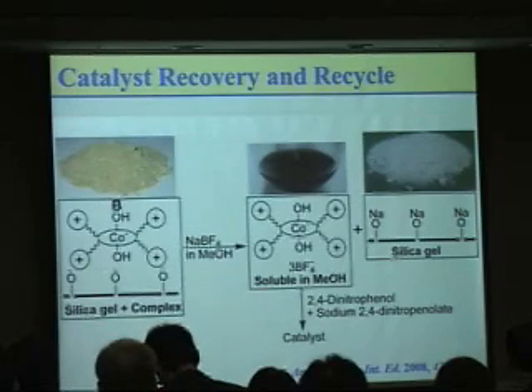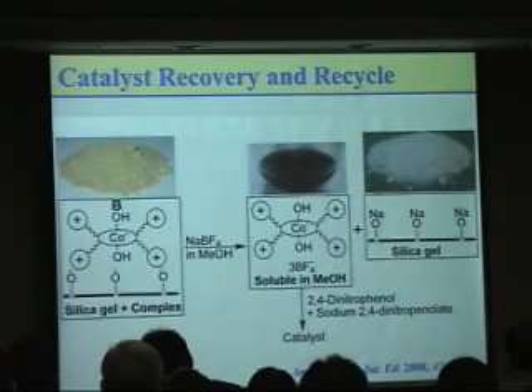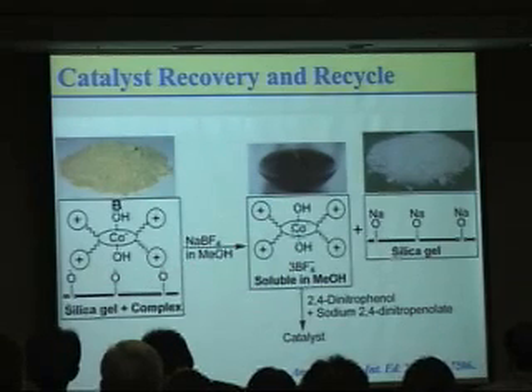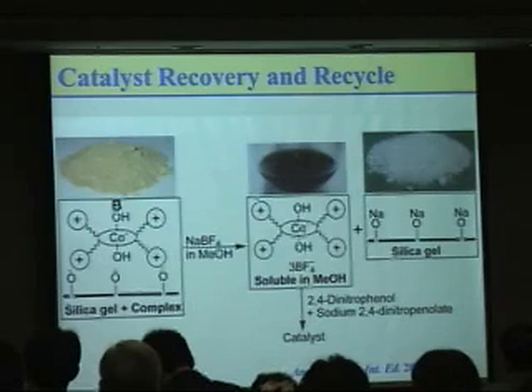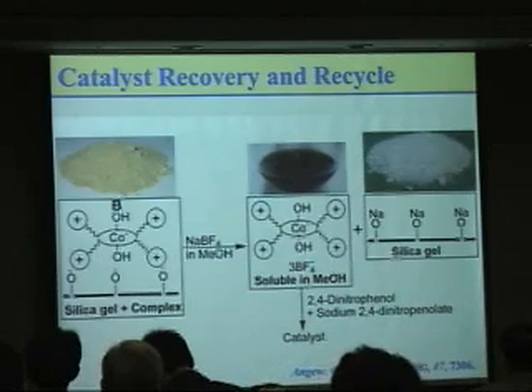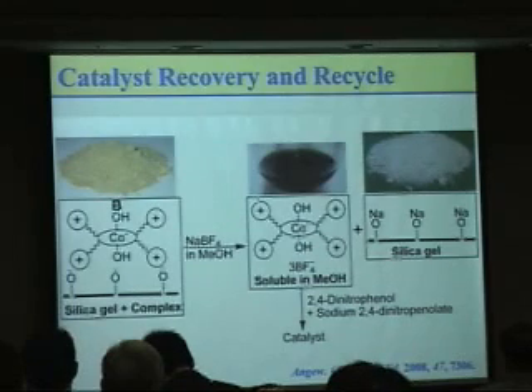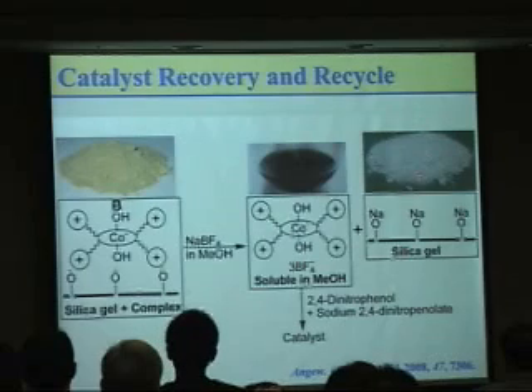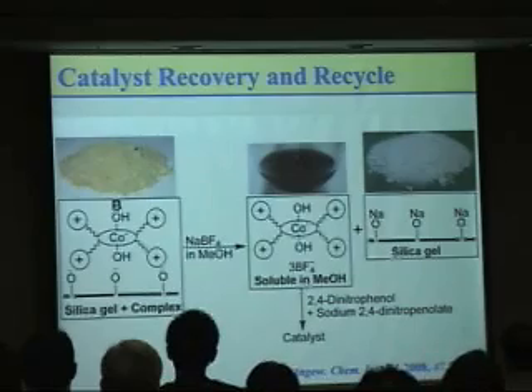When this silica cobalt composite is dispersed in just methanol, nothing was extractable. But when I added sodium tetrafluoroborate, an anion exchange reaction between the surface siloxide anion and the tetrafluoroborate occurs, liberating the cobalt complex into the solution phase. And the extracted cobalt complex can be converted to the active catalyst by simple treatment, and we can also reuse the silica gel by just washing with acid.